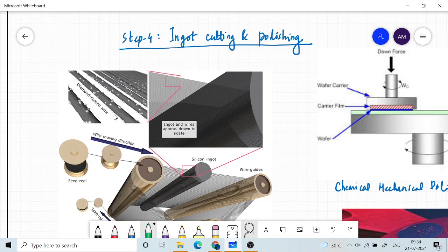Okay, something like say a 10 centimeter wafer, you can have less than 0.5 millimeter thickness. But if you are talking about a 30 centimeter wafer, then you require more thickness in order to support it mechanically. Okay, but ultimately we are going to make our devices only on one side of the wafer, and it is basically a surface. So out of this say 700 micrometer, our fabrication will be taking only some of the top region,